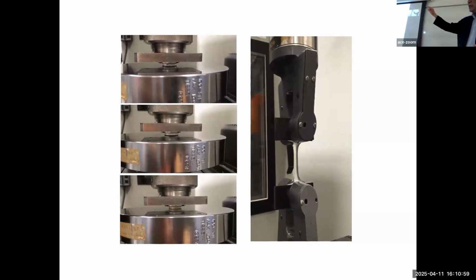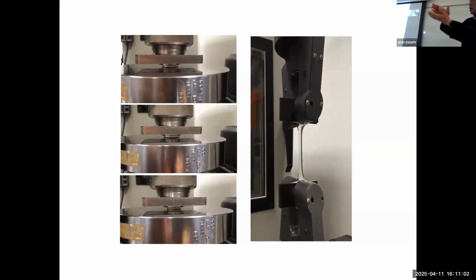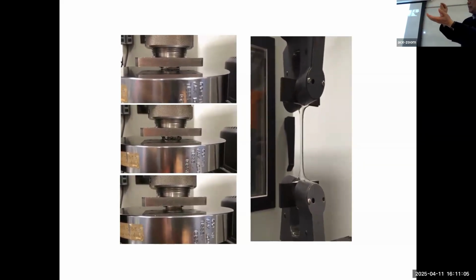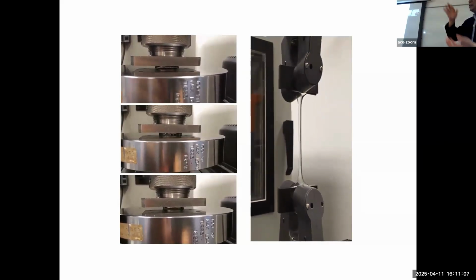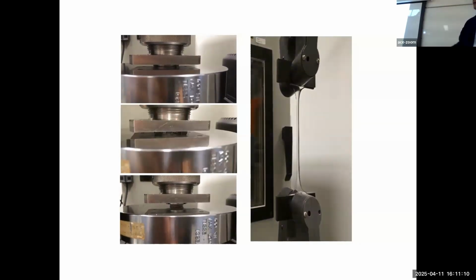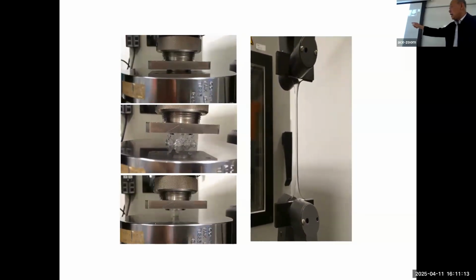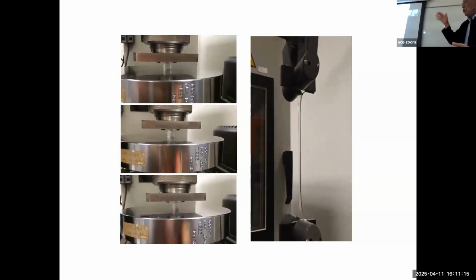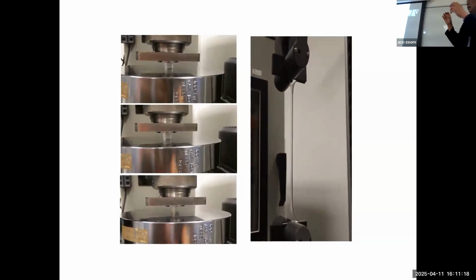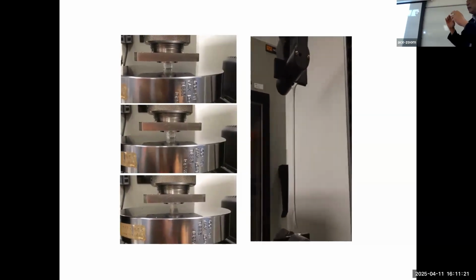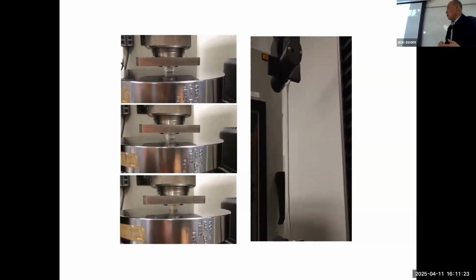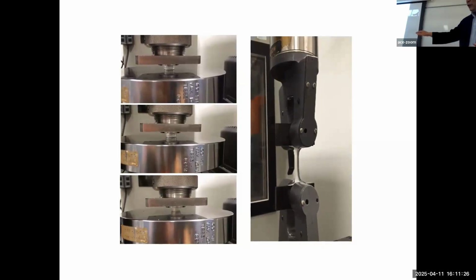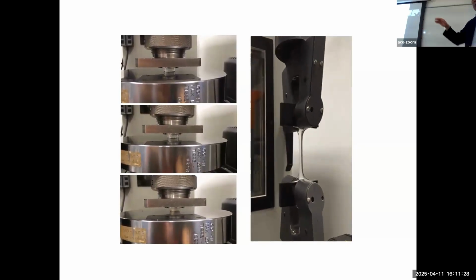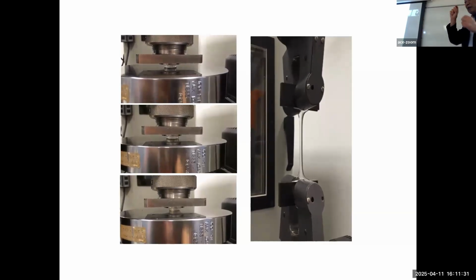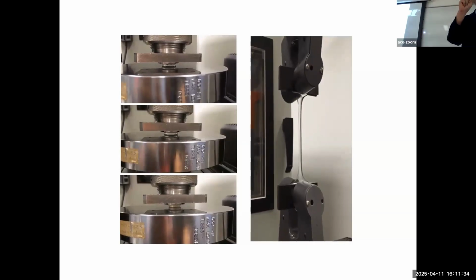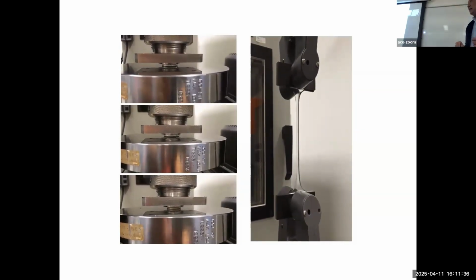If you pay attention, you can see for the first one, top one, when you compress, they become very thin. But when you remove, they cannot recover. That means it completely lost its elasticity. For the second, after removing the force, all the hydrogel was broken. It's very brittle, okay? Only for the bottom one, after you remove the force, it will recover to the original size. So that means it has very good elasticity.